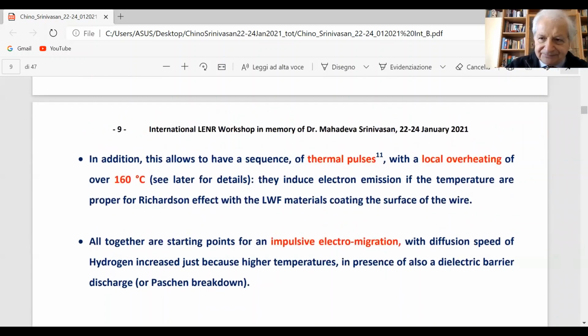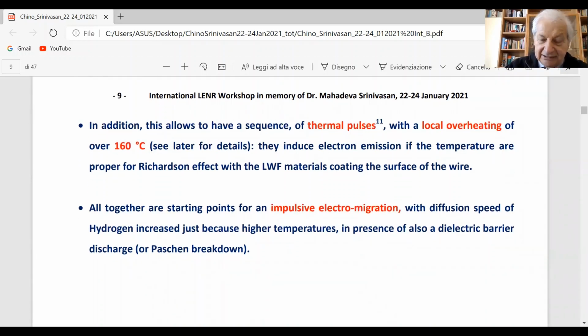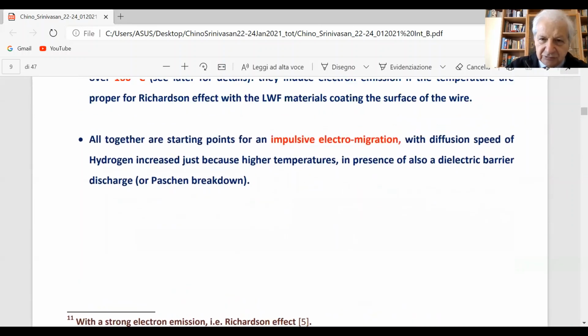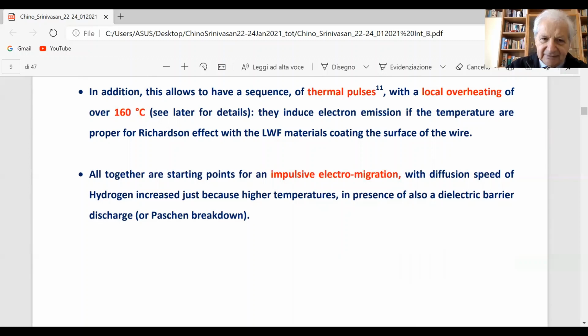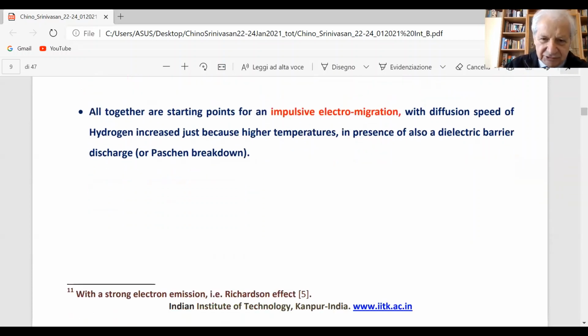The overheating due to the pulse is quite large. In our typical condition, 160 degrees. And the electromigration effect is very strong, of the order of 2-3 volts per centimeter, about 4 or 5 times larger than the usual electromigration effects. So the whole system has very, very strong non-equilibrium conditions.